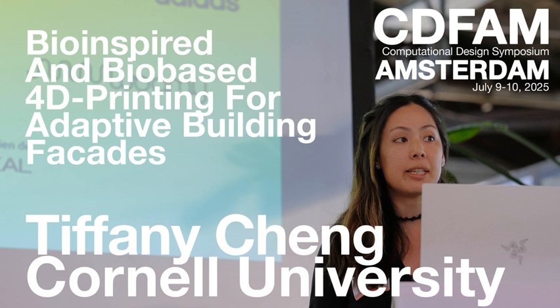And so based on this large-scale additive manufacturing platform that we developed, my master thesis students also explored the unique properties of auxetic metamaterials, which when bent, form surfaces with variations in double curvature. So they exploited this property in self-forming bending active shell structures in which the wood is distributed and embedded within a surface with this honeycomb and inverse honeycomb pattern. And depending on the pattern, this results in positive and negative Gaussian curvatures. In other words, that's like a dome-like curvature or a saddle-like curvature.